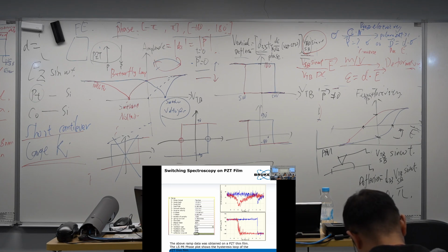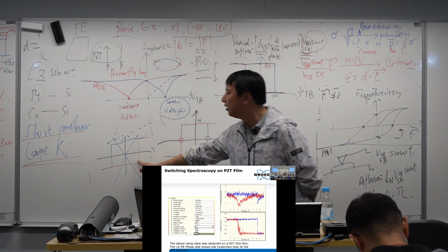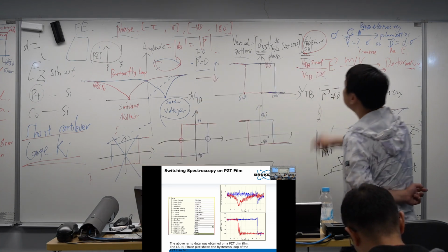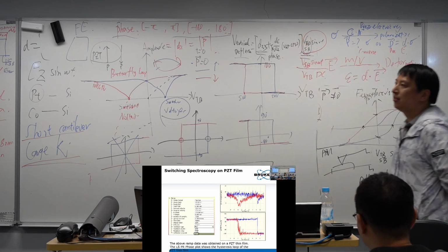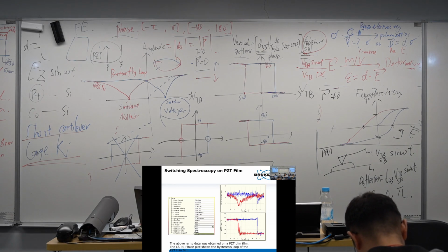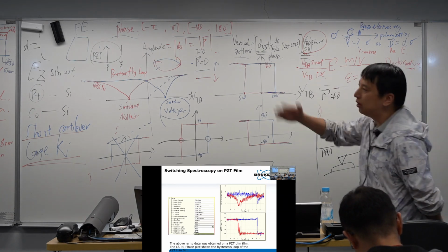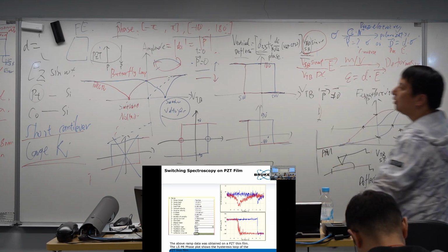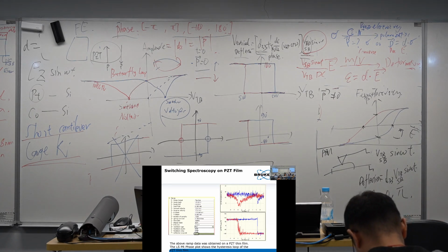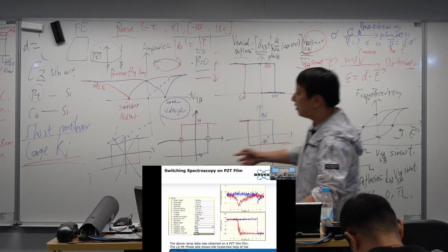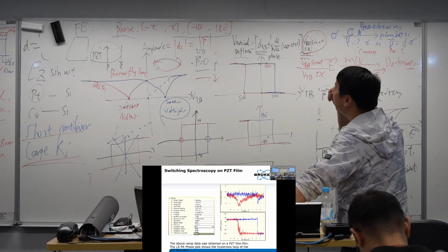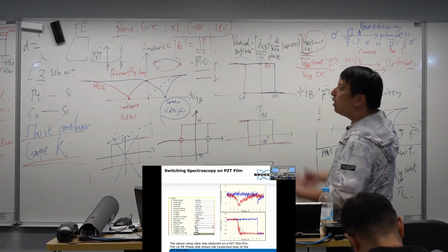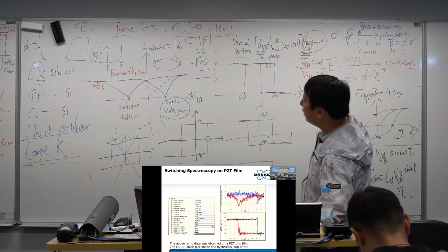Okay, sometimes in your experiment you can get a loop something like this. The reason you can get a loop like this is because you still have the surface potential. And the surface potential can be changed by your tip voltage, because you are actually injecting ions or injecting electrons. So if you find something like this, the direction is wrong, it just means we still have the potential. Okay, so once we are really measuring ferroelectricity, it's only like this.